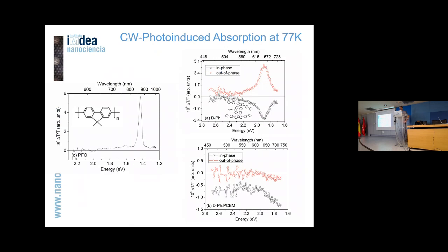These are very often questions that we have. So we can do this sort of experiment, which is CW photo-induced absorption. What we do is freeze the system, go to 77 Kelvin, and then photomodulate, basically photoexcite with a rectangular laser shape, and see the change in absorption. So you can resolve the absorption bands with triplets, and compare if these bands appear in the pump-probe measurement you are recording. In that way you can discard whether you have any.